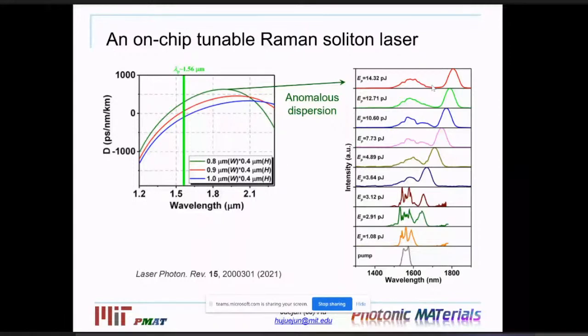Now, because we have a very short pulse, due to the very short time duration, in the spectral domain it also gets broadened. It contains different spectral components. Right? So because of the dispersion, the shorter wavelength components will start to pump the longer wavelength components via Raman interactions. So the net result is that as the pulse propagates through the waveguides, you see a red shift of the spectral components.